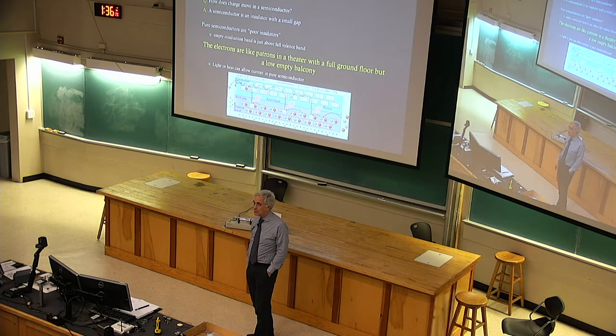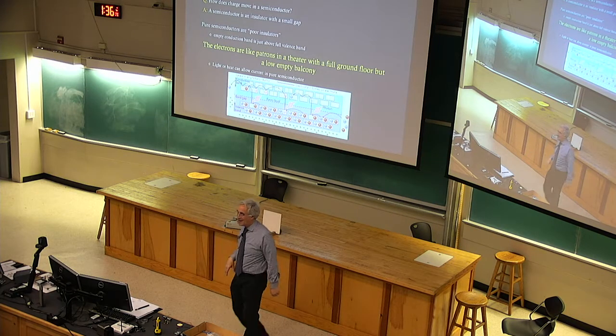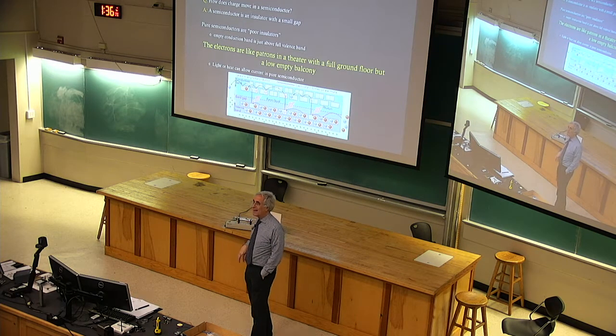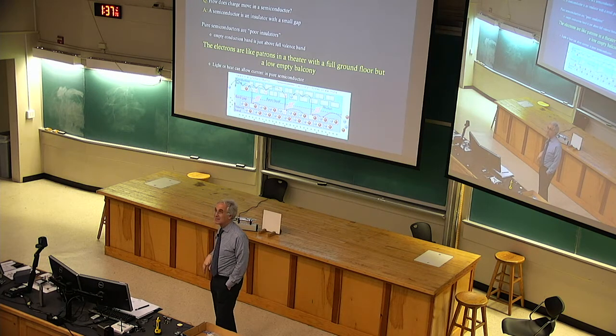That's not what this drawing is showing you. But I'll tell you that's an important effect, and that is one of the reasons why you don't want your electronics to overheat. If it overheats, the silicon stops being what it's supposed to be, namely an insulating thing, and it becomes more of a conducting, metal-like thing because it has electrons up there in the conduction band that can move. That's a problem, and it misbehaves and often destroys itself. So semiconductor devices work best when the temperature is kept under control. So that's the public service announcement piece.